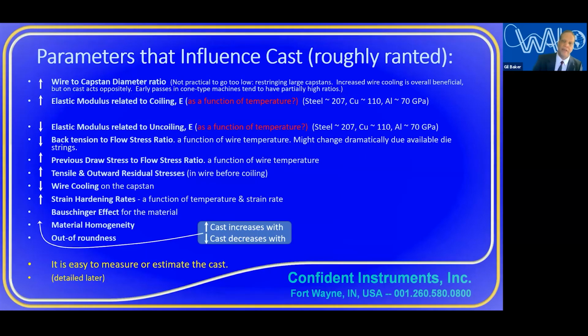Now, a lot of people are asking, what factors cause cast? Again, I'm going to remark down here, it's very easy to measure cast. So that's probably the first thing you should do. But what parameters do influence it? People want to know what processes are going to have more cast. And the main parameter is the wire to capstan diameter ratio. Again, I showed that with the wire on the mandrel. If a little wire is on a big mandrel, it might stay elastic. But if a big wire is on a small mandrel, then you're going to have more yielding.